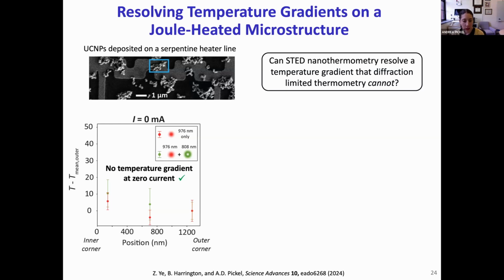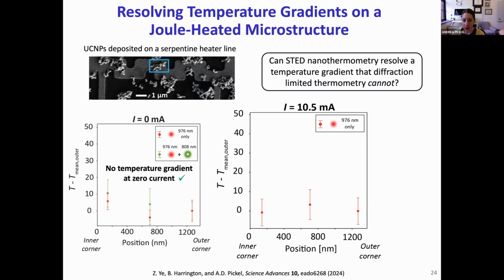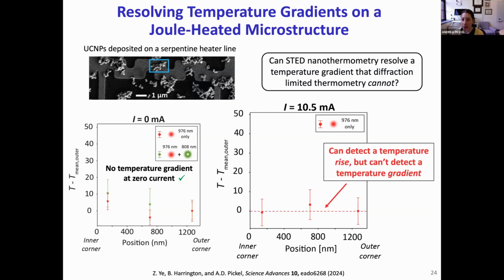And I also want to mention that one challenge we're still working to address is that the STED laser can heat optically absorbing low thermal conductivity materials like nichrome. So there's also a laser heating contribution that's being subtracted off here. Next, we apply a DC current to the heater line. And starting with the diffraction-limited measurements, we indeed observe a temperature rise as expected. However, the data points are again essentially flat, meaning that we can't detect a temperature gradient.